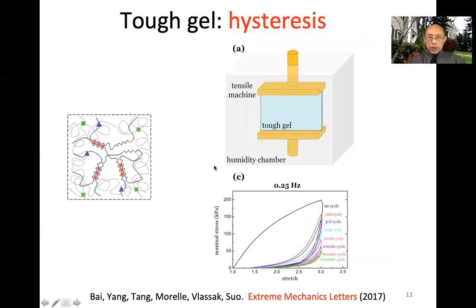However, when we do this experiment without any cut, on a tough gel, just a stress-strain measurement but with cyclic loading, this is stress plotted against stretch. First cycle loading up, this is the stress-strain curve. When you unload, you follow a different path. You have enormous hysteresis corresponding to the unzipping of these ionic crosslinks.